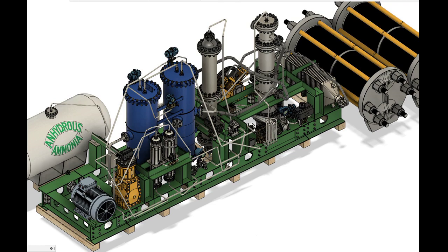But with coal, natural gas, or municipal solid waste-based hydrogen sources, impurities, especially permanent poisons such as sulfur, become a much greater challenge. In fact, the biggest challenge encountered by the designers of early ammonia plants was not making sure the high-pressure converter didn't blow up, but rather producing a constant stream of ultra-high purity hydrogen gas from the very dirty coal sources that were available in 1920s Germany. Extensive scrubbing, washing, pressure swing adsorption, and zeolite adsorption are required for these dirty sources.